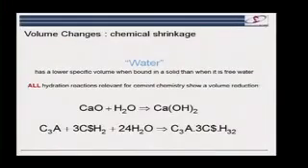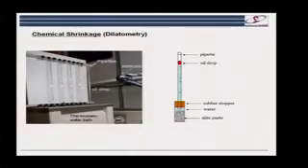And the reason for this overall volume decrease is quite simple. When you have water moving around in the liquid, each water molecule occupies quite a large amount of space. When you pin that water molecule down in a crystal, on average it occupies less space. And that's why you have this chemical shrinkage. And it's quite nice because it provides us with a very simple and cheap way of following the hydration process.